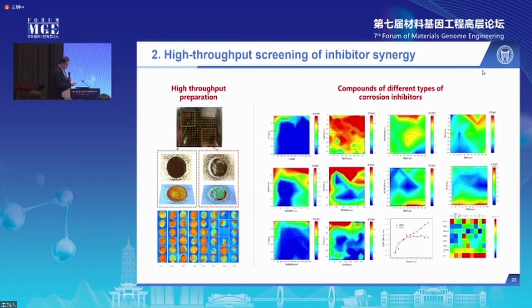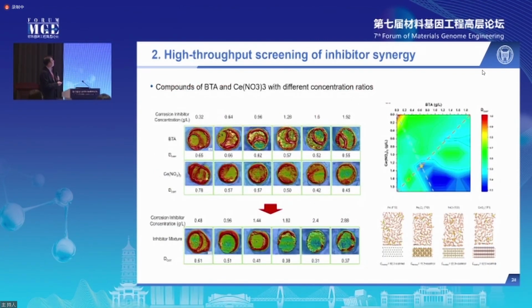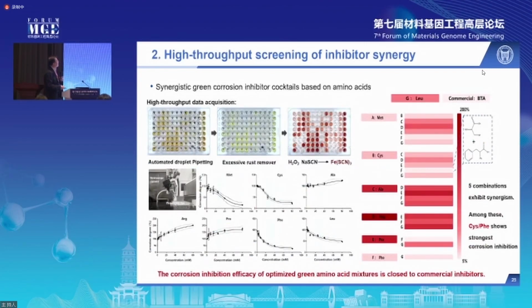And this is an example showing the compounding of two common inhibitors, BTA and cerium nitrate. This is an adsorption type inhibitor, and this is a precipitation type inhibitor, and they have two different mechanisms. And after mixing them in a good ratio, we can really suppress the corrosion very effectively. And this is showing a high throughput screening of an amino acid based inhibitor mixture.